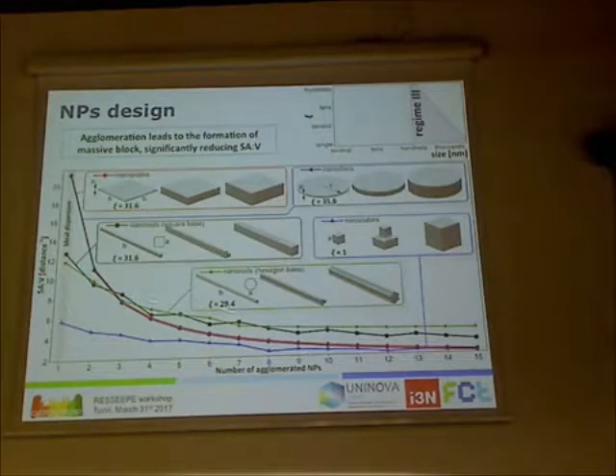So those that still keep the highest ratio, even under agglomeration, are the nanorods. Indeed, these are the most suitable particles to be designed because, as you always have this kind of aggregation, we can still have this surface area ratio very high.